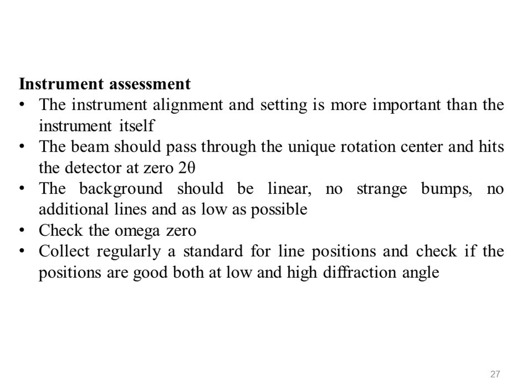In most cases, the instrument alignment and setting are more important than the instrument itself. Be paranoid on alignment. The beam should pass through the unique rotation center and hit the detector at 0 two theta. The background should be linear, no strange bumps, no additional lines, and as low as possible. Check the omega 0. Collect regularly a standard for line position and check if the positions are good both at low and high diffraction angle. Check also the rest.